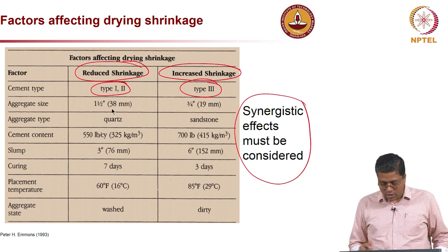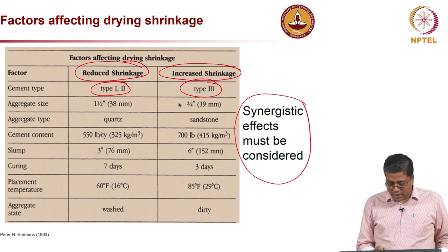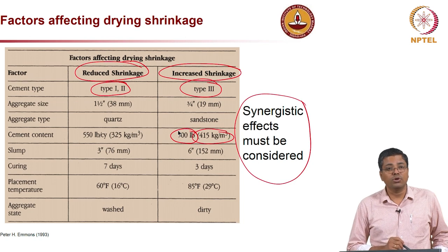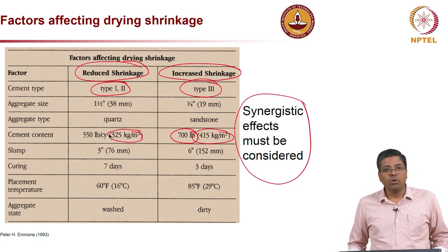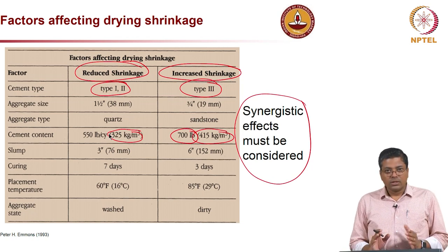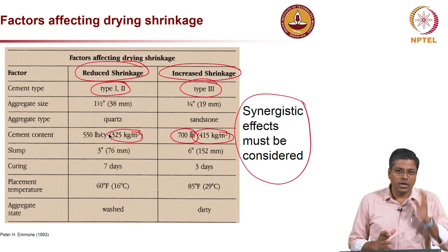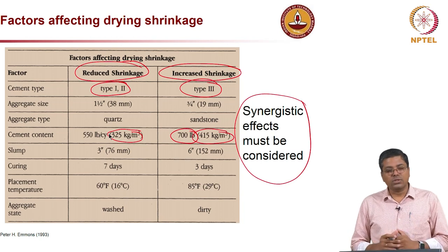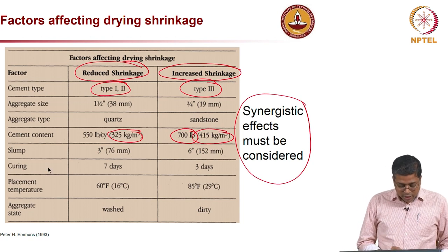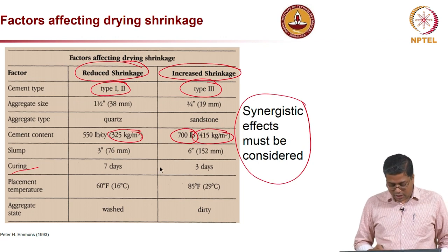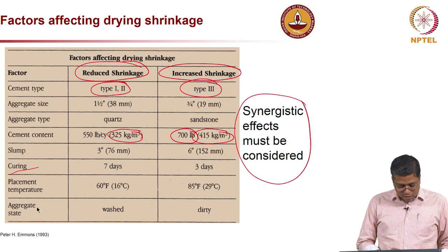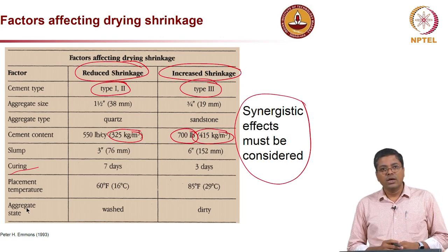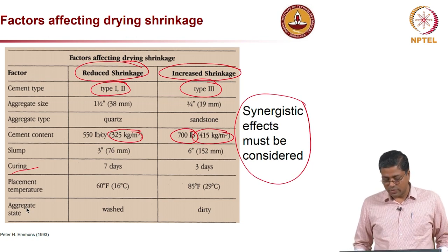Definitely aggregate size also; if you are going for smaller size aggregate, you might have a higher shrinkage. If you go for a large cement content, like say 415 kg per meter cube instead of 325, you can have more shrinkage. See, cement is the ingredient in concrete which leads to shrinkage. So if you can reduce the amount of cement in concrete, definitely you can reduce the amount of shrinkage. And curing: if you go for a shorter curing, here 7 day versus 3 days, the 3 day case is exhibiting higher shrinkage, and also the quality of the aggregate matters. So all these factors must be looked at, but synergistic effects must also be considered when you look at shrinkage.